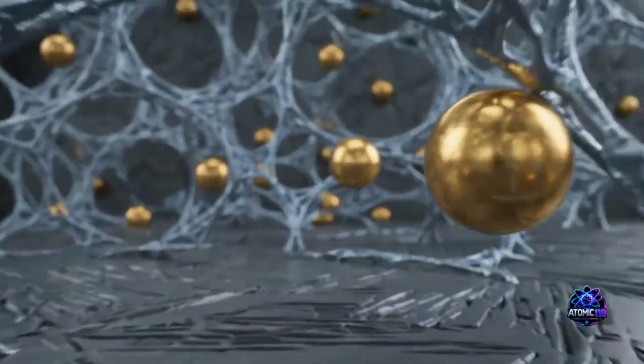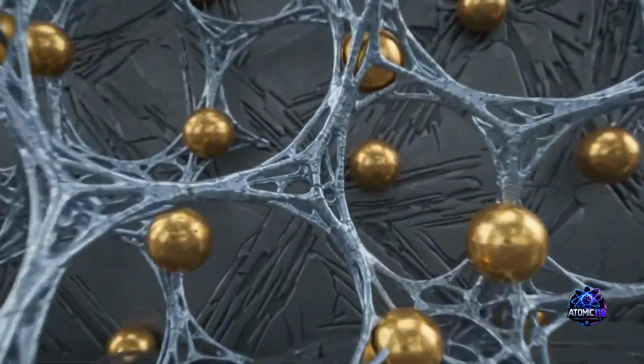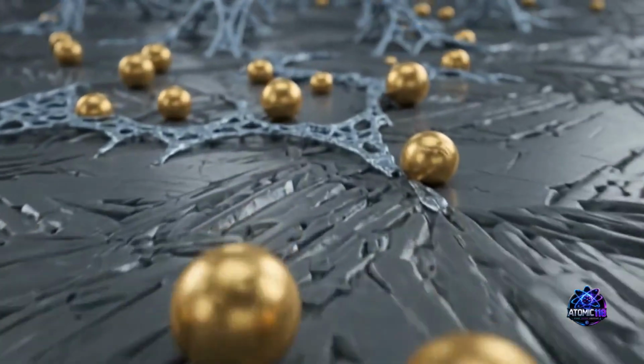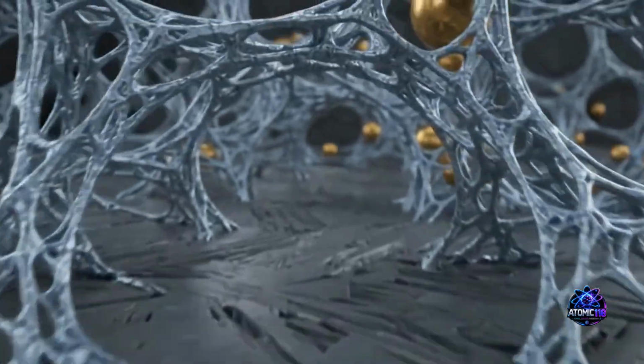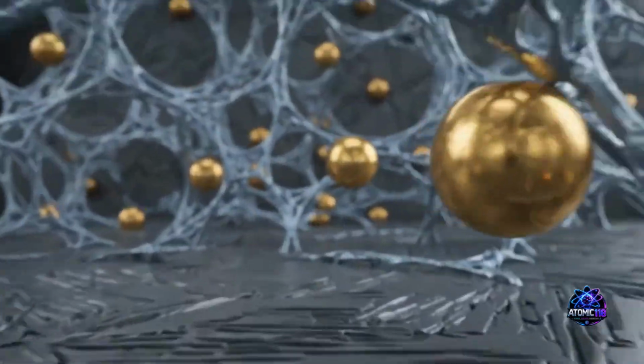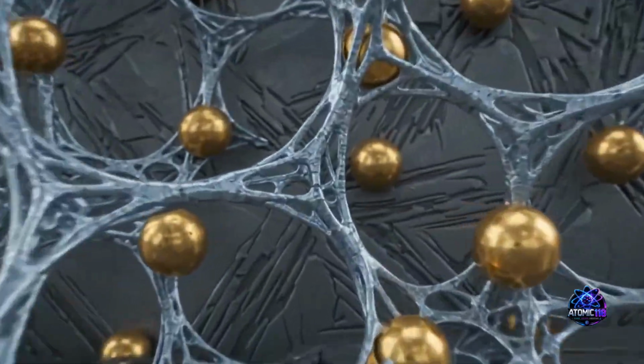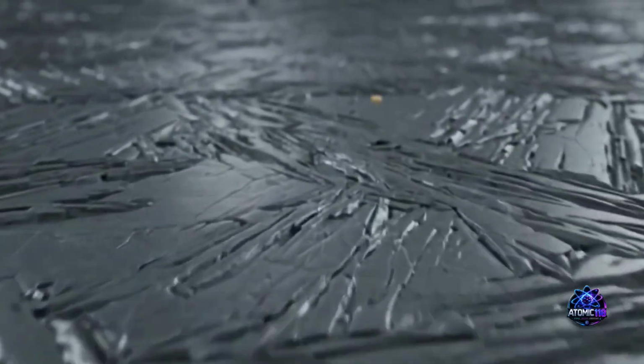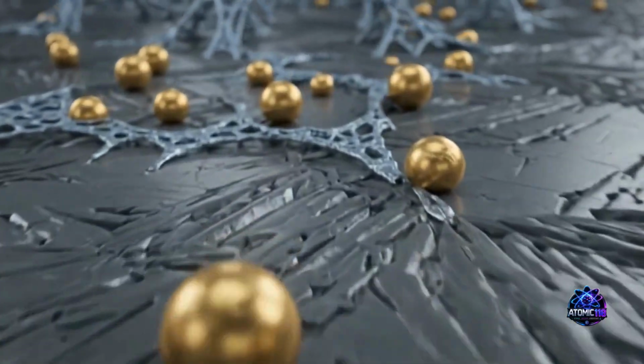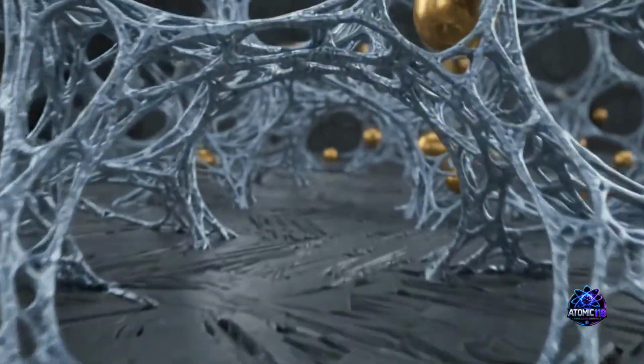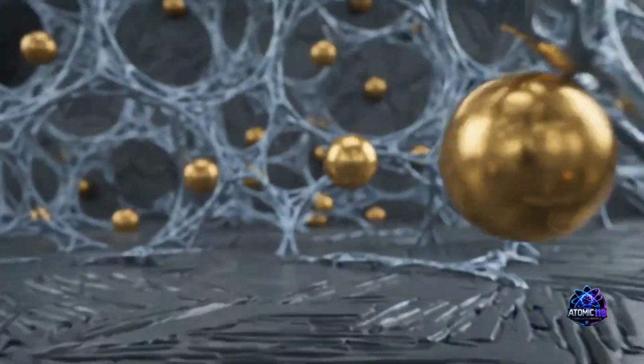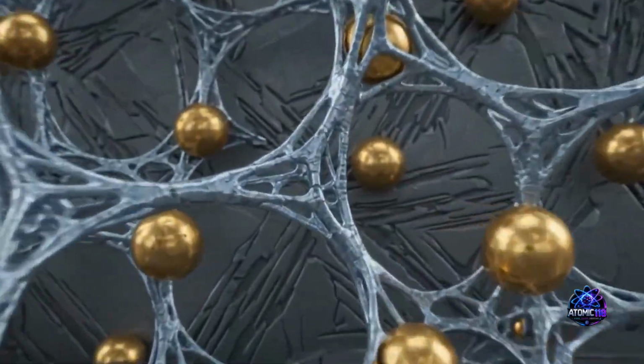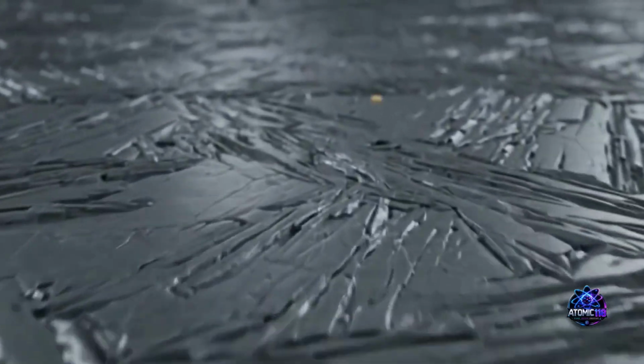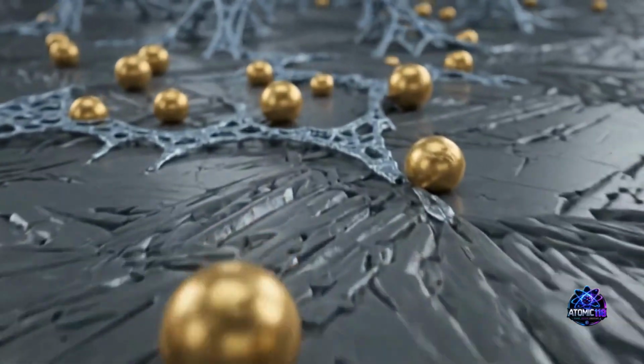Yeah, exactly, T-Rex arms. So if molybdenum is at the peak of the cohesive energy volcano, vanadium's contracted orbitals drop it into a cohesive energy crater. The atoms just can't hold on to each other with the same grip. They really can't. The orbital overlap is incredibly poor. And because those outer electrons aren't being utilized effectively for interatomic bonding, their spins unpair. Wait, unpair? Yeah, and this unpairing actually generates magnetic behavior in pure vanadium.